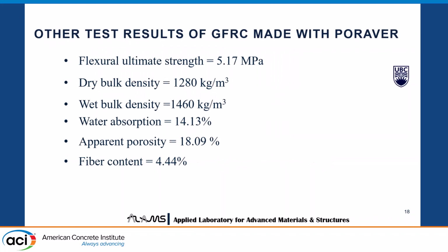So these are the additional tests that we did on only the poraver concrete. So we got a flexural strength by 4-point bending of 5.2 MPa, and the bulk density dry basis was 1280, wet bulk density was 1460, and the water absorption is 14%, porosity 18%, and the fiber content from our test we found is 4.4%, 4.44 to be exact.